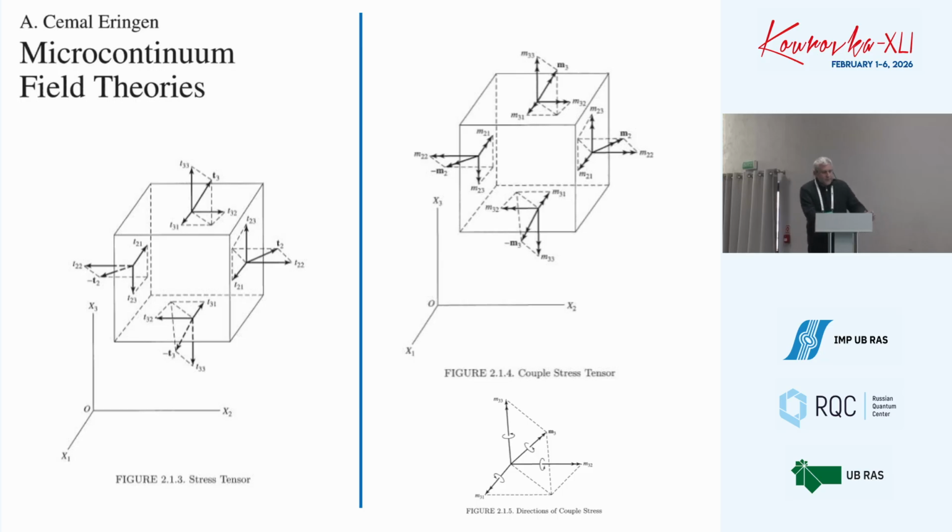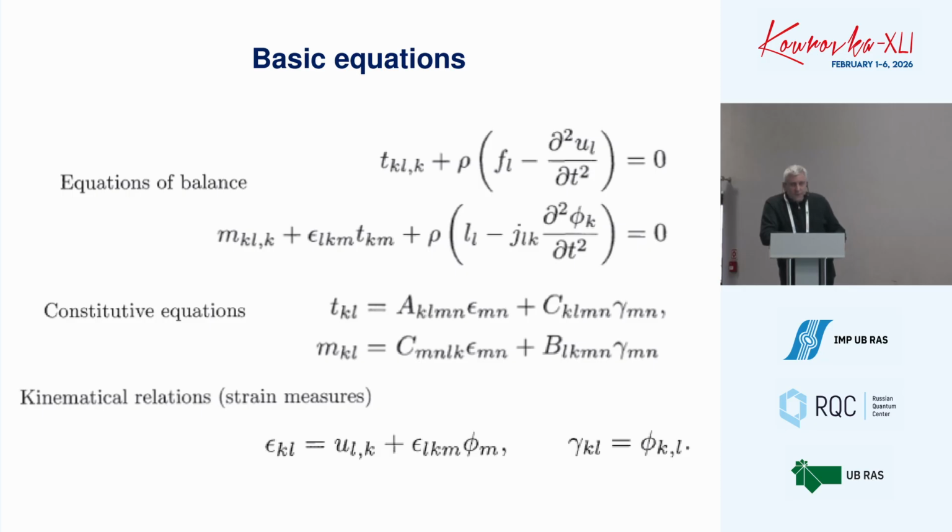To apply this approach to this crystal, I briefly explain the basic equations of the micropolar theory. Beyond the expansion of the strain tensors, we have to introduce an additional stress tensor. Of course, we have the stress tensor, shown in the left panel, but we also have to introduce the couple stress tensor, which shows how the moment of momenta is distributed over the faces of the microvolume. The basic equations include the so-called equations of balance, which are nothing other than Newton's laws for the displacement field and rotational fields, where rho is the mass density, small j is the micro-inertia tensor, F is the density of force, L is the external torque, and T and M are the usual stress tensor and the couple stress tensor.